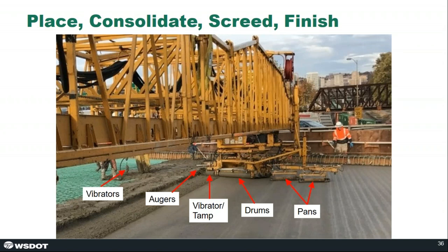Now about placement and screeding. So the process is shown here, going from right to left. At the leading edge, we have laborers with immersion vibrators to consolidate the concrete. The finishing machine following that, which we require on all bridge decks, has augers at the front end to distribute the concrete more evenly, followed by a vibrating tamp to perform some secondary consolidation after the augers have moved some of the concrete. That's followed by rotating steel drums, which actually strike it off to grade. And the drums are followed by two pans that are dragged across the surface for final finishing.